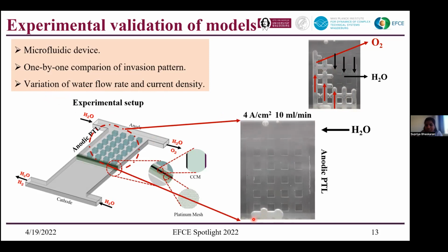Yeah, so here you can see how the reaction occurs at the catalyst layer, and we could see the oxygen bubble moving towards the porous transport layer. So once it reaches the end or near to the flow channel, we could observe the removal of this oxygen bubble and again refilling of the system. So here we are sending water at a flow rate of around 10 milliliter per minute. And we could also observe one more interesting fact: the pathway of oxygen stays constant throughout the supply of current, until the process is stopped. So this is one of the most interesting findings that we had in our group. But since it's a more homogeneous network and there are a lot of artifacts in the cell, this is actually a prototype.